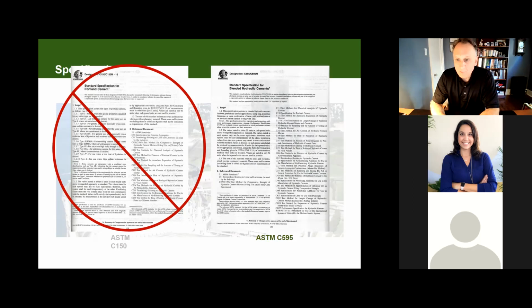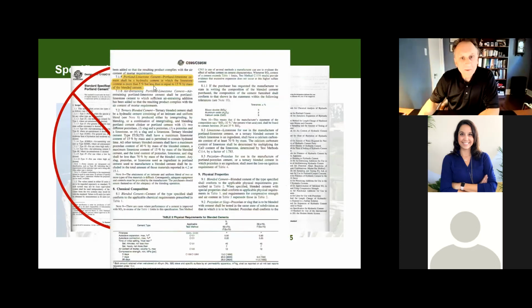Now, why on earth would we use C595? Well, because that document, and boy, I'm clicking, it's awfully slow, says to make Portland limestone cement, Portland limestone cement shall be a hydraulic cement in which the limestone content is more than 5%, but less than or equal to 15% by mass of the blended cement. So what C595 does, it allows you to use more limestone in that 1 ton of cement that you're going to market to the concrete producer.